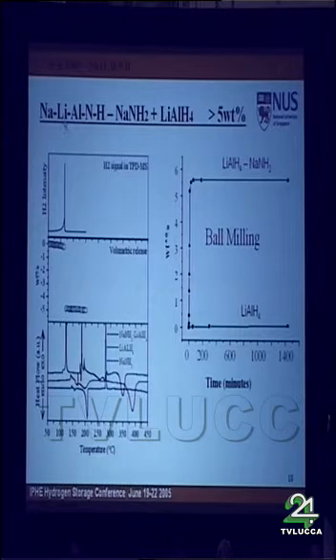In this system, we mix sodium amide with lithium alanate and try to find out what is going on in the system. It's quite different from the previous system because it is an exothermic reaction. We simply mix these two chemicals and conduct temperature programmed desorption. We notice there's more than 5% hydrogen desorption at a temperature around 110. It is an exothermic reaction.